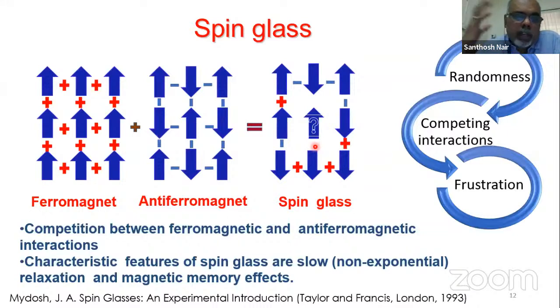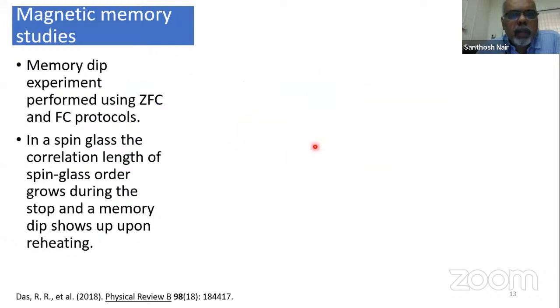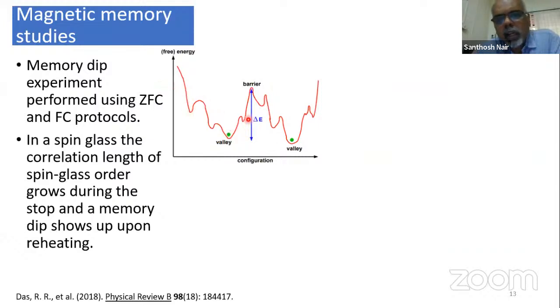And considering that you have mixed valency, the presence of cobalt 2+, cobalt 3+, manganese 3+, manganese 4+, there can be interactions between each of these, such as manganese 3+ and cobalt 3+, manganese 4+ and cobalt 3+, etc. So there could be fairly large, complex interactions between these ions, which can lead to a glassy characteristic, right? When you have a magnetic glassy system, you also see some memory effects. Essentially, the system has, as I said, several local energy minima which each can freeze into, and so we can have a memory effect corresponding to that.